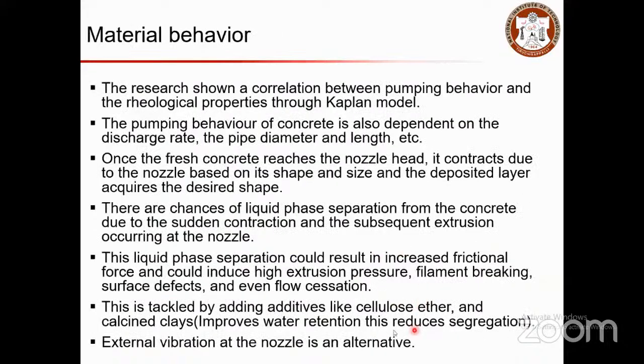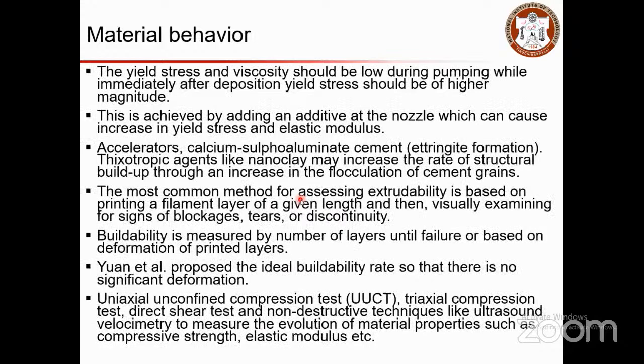How does this work? This is based on rheology, and you need to customize the rheology of the material. The additive materials that you use in the cementitious material should have free flowability, so that when you spray the concrete, it can freely flow. It comes through the nozzle and is placed in layers and required shapes. If you look at the material behavior, yield stress and viscosity are the two primary properties that we need to look at, which should be low during pumping, while immediately after deposition, yield stress should be higher in magnitude. This is achieved by adding an additive. The additives should control the flowability of the mix coming through the nozzle, which increases yield stress and elastic modulus. Accelerators can be added so that the strength gain will be significantly high, so the layers can withstand the load once they have achieved the strength.